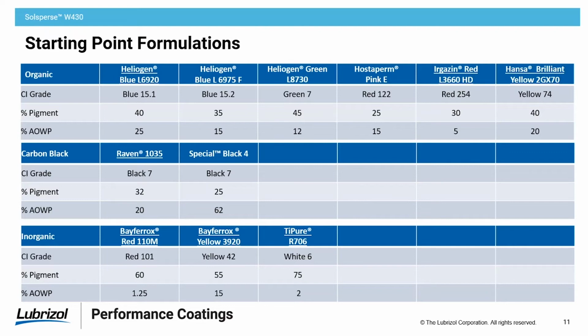And if you look at the additive on weight of pigment relative to the percent pigment, we are generally following that surface area divided by 5 equation. And you can see that for the most part, the amount of dispersant that's actually being used is fairly modest until we get to the high surface area carbon blacks, like the Special Black 4, for instance, which has a very, very high surface area and because of its much smaller particle size, does have a higher dispersant demand. But in general, for the industrially significant pigments, the dispersant demand is right in keeping with what we would expect.